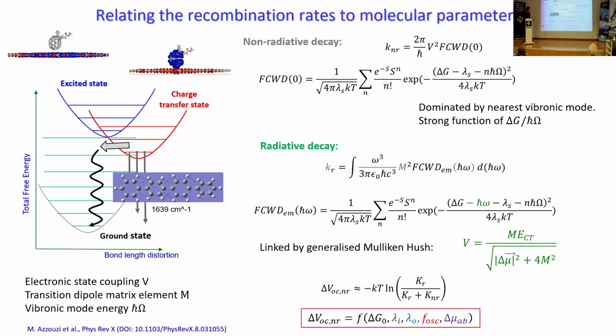And when we look at the origin of those vibrational modes, they're connected with the pi conjugated system, with the carbon-carbon double bonds that underlie all organic semiconductors, and it's quite hard to eliminate them. And so that looks as though it may be a showstopper, and it's certainly part of the reason why these non-radiative voltage losses in these materials are high.